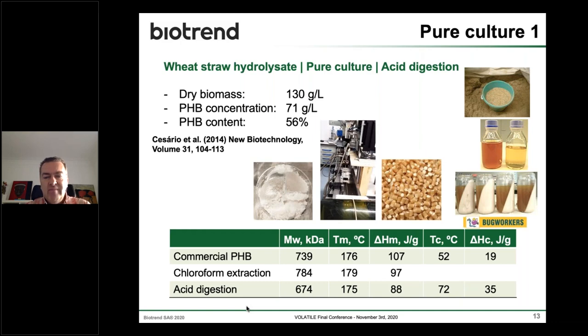So on the bottom table you have specifications of the commercial PHB, and this was the PHB homopolymer, and you also have the properties of the polymer that we produced in the lab as extracted by chloroform extraction. And chloroform extraction is a method which is very good for analytics, because it does not break down the polymer. It maintains the native properties of the polymer. And then we performed an acid digestion. It was okay. The properties were maintained to a very good extent, but we were not very happy with using concentrated acids as a digestion process due to several constraints, including compatibility of equipment with the acidic conditions, which would require very expensive equipment to implement this process.